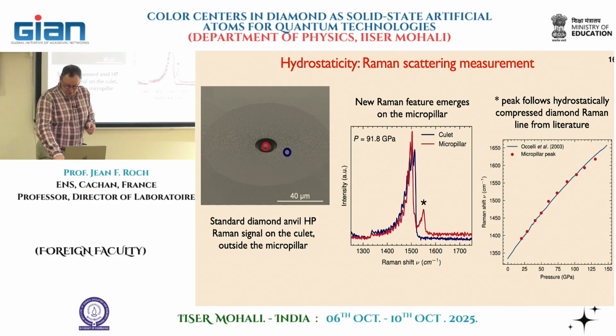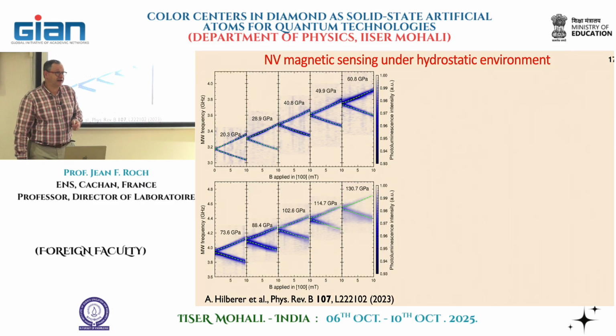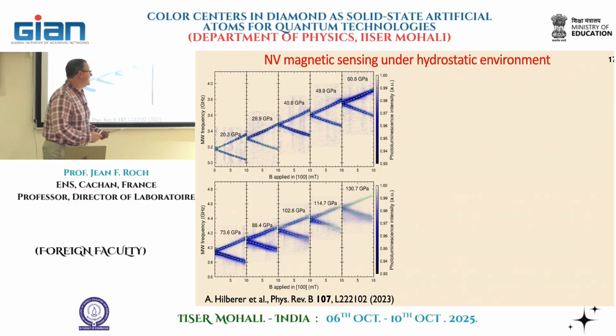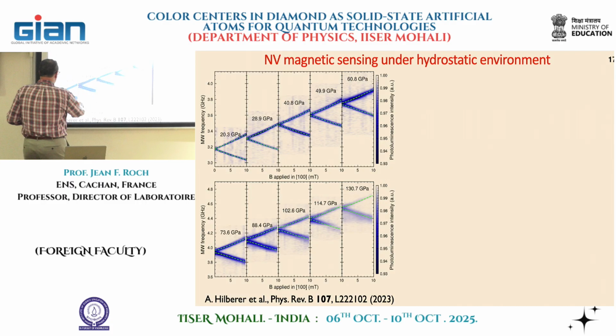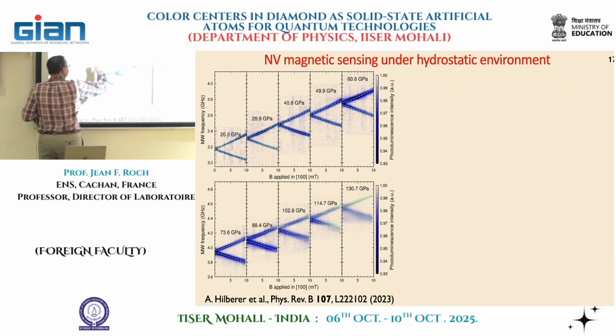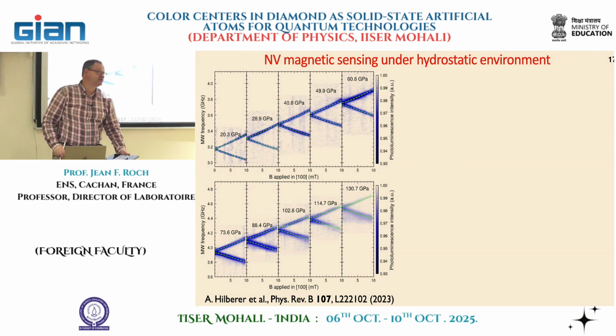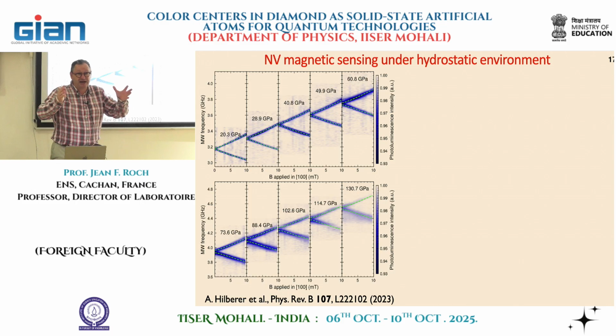So now let's look at what happened to the NV signal. And you see that we keep the Zeeman shape. The Zeeman dependence is kept now. We no longer have the mixing of the states that led to this great splitting even at zero field. But there is only now a shift of the line associated with the dependence of the D parameter with pressure. So two electrons simply getting closer. But nevertheless, the C3v symmetry is maintained, and we keep the ODMR contrast.